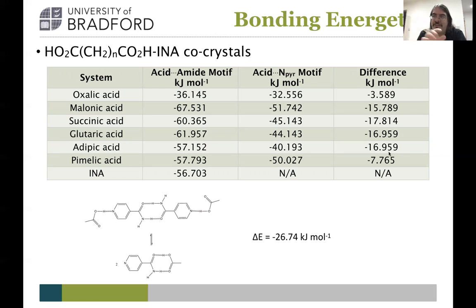And we see, beyond the first and last one in this set, it's relatively consistent as you change the length. So why aren't we getting the hydrogen bonds we'd expect from purely being driven by the lowest energy system? And of course, what we've got to consider is not the formation of the dimer itself, but the motifs within the crystal. It's this tetramer. That's the consistent feature. And so if we form the tetramer, we're going to form two acid pyridine hydrogen bonds as well as that dimer in the middle. Now, we could consider breaking that up and forming two acid-amide hydrogen bonds instead. Instead of having a tetramer, have two dimers forming. And if we calculate the energy difference between that system, we find the tetramer is about 26, 27 kilojoules per mole lower in energy than the one we don't see.